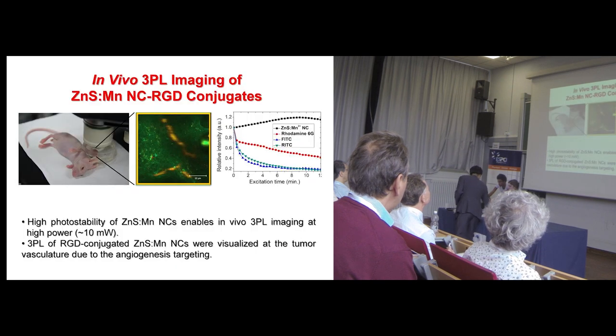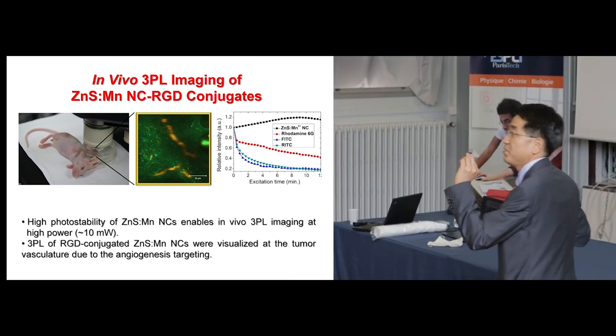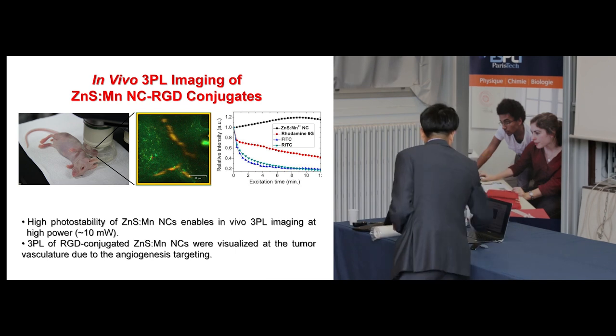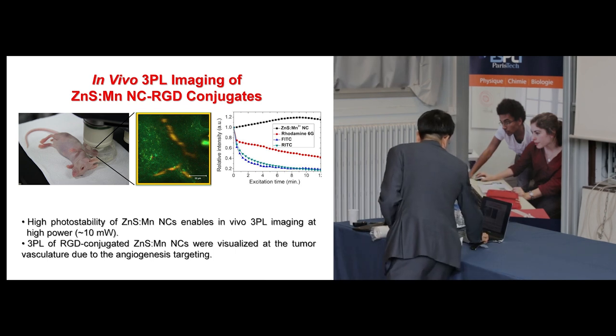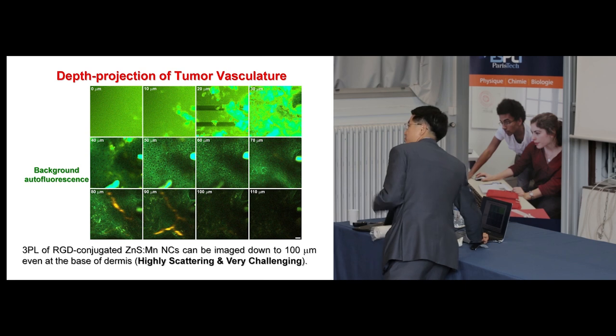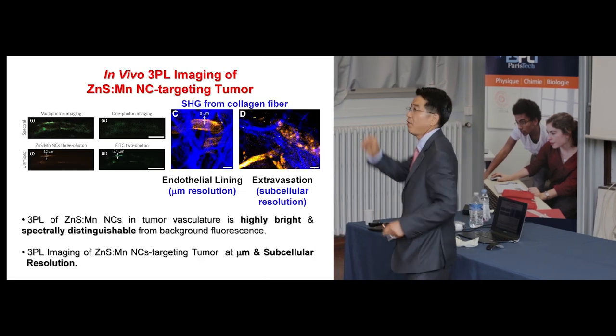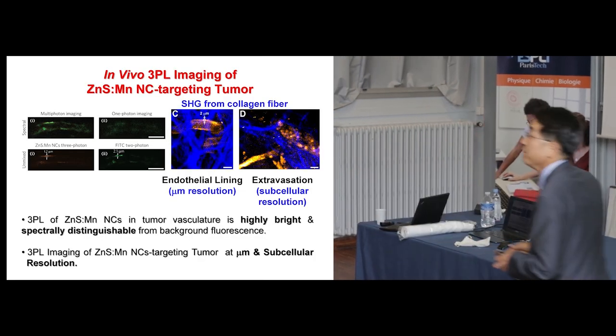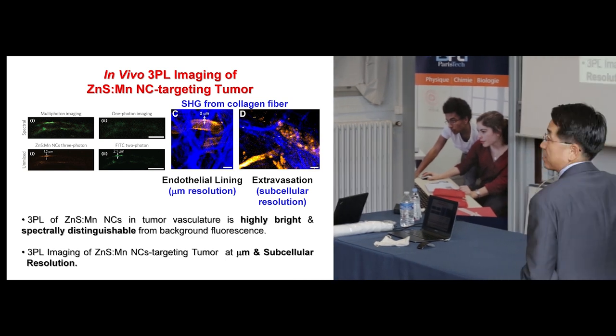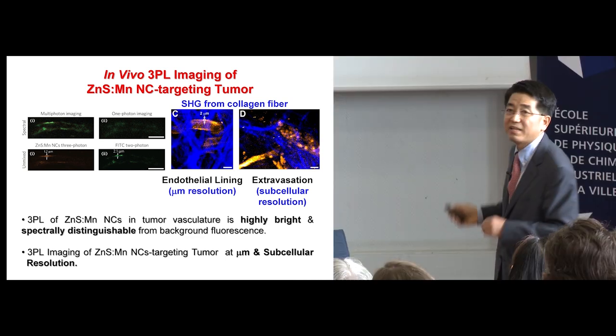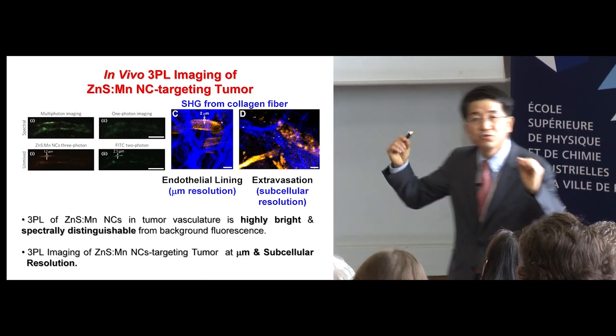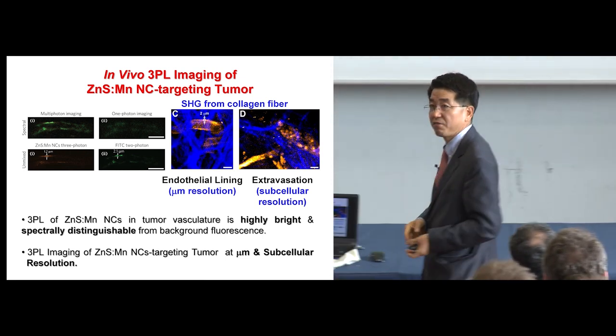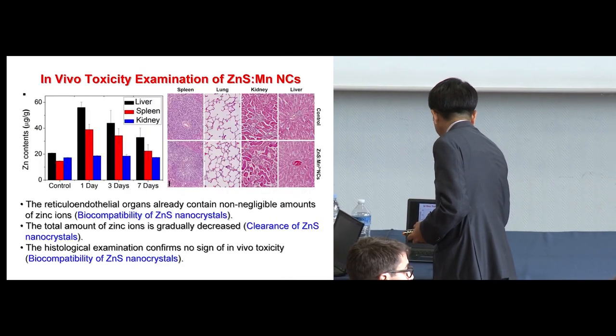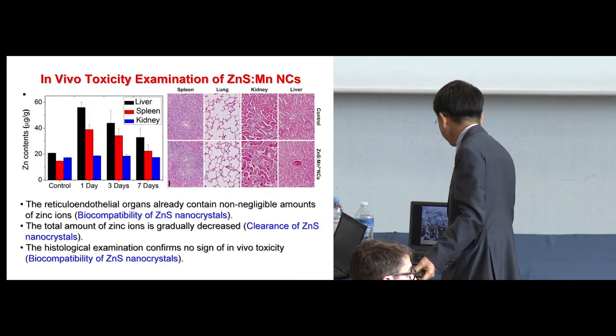Furthermore, we did the in vivo imaging. As you can see, for the first time in vivo 3-photon imaging is possible because of these highly bright quantum dots. We can see deep inside, and also have higher resolution. This is in vivo. You are looking at a blood vessel where a thickness of less than 2 micrometers can be resolved using this new 3-photon imaging probe. With that also comes less toxicity, that's obvious.